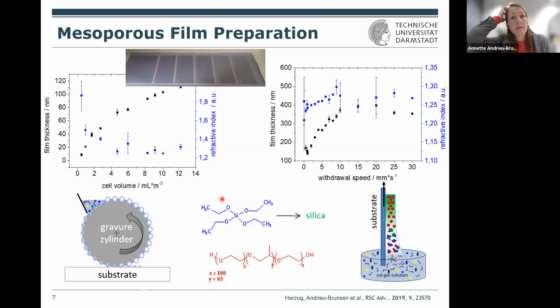Yeah. But this is on the sol gel chemistry, and then you have a flexibility, let's say, between mesopores up to maybe 30, 35 nanometers. And if you want larger pores, then you have to go to different type of pores, let's say. So the sol gel chemistry with this assembly process, that's at least what I have in mind, goes to 30, 35 nanometers maybe.